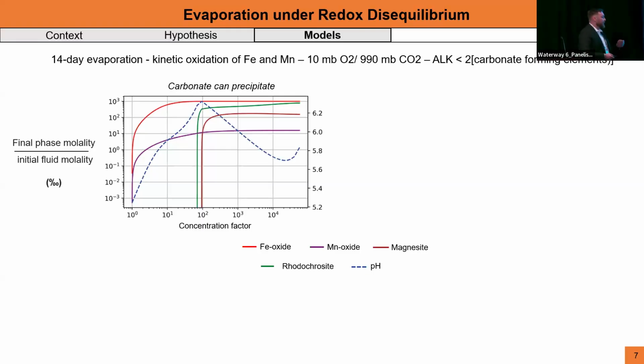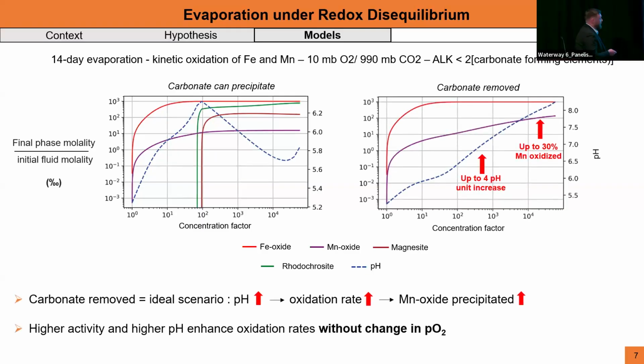But now, if you consider a perfect case where you remove these carbonates, a very interesting thing happens: the pH will continue to rise as you concentrate. And the pH is going to rise quite a lot, up to 4 units, which allows this time the manganese to oxidize, and up to 30% of the manganese present in solution will form manganese oxides, which is quite significant and observable in situ, for example. And this without any change in partial pressure of oxygen.